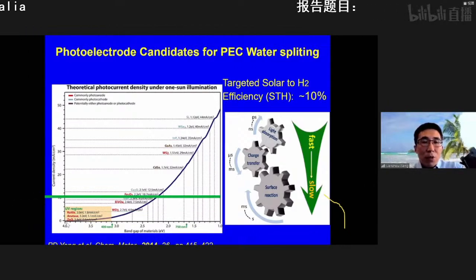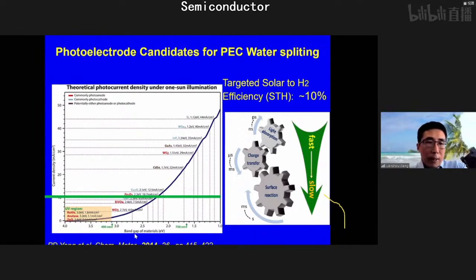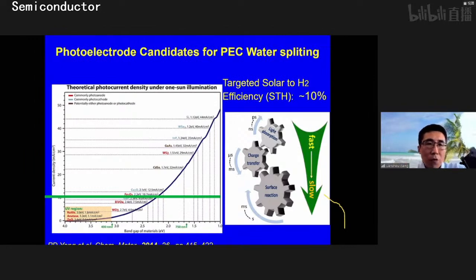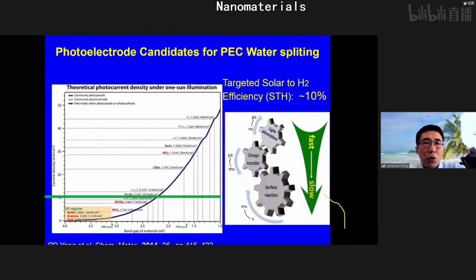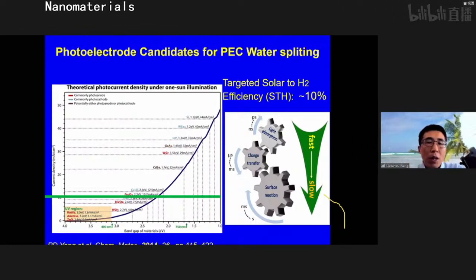But unfortunately, if you look at most of the available catalyst and photoanode materials, like TiO2 and tungsten oxide and some other oxide materials, they still have relatively low theoretical photocurrent performance. But we're still interested in this category. The reason is that if you really want solar hydrogen to be produced at low cost and also be stable, we really need to use cheap and stable materials other than this type of group 3-5, very expensive and unstable material.